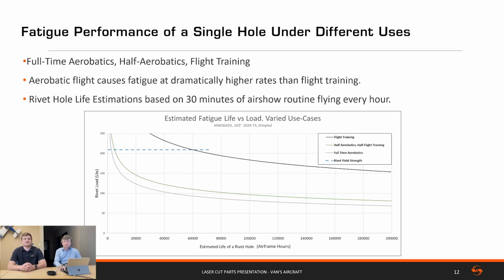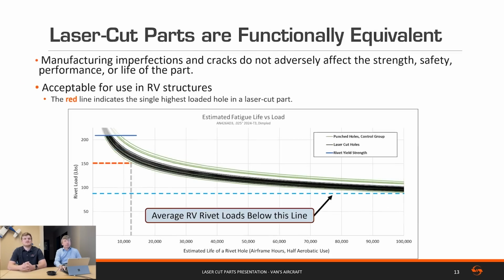So these calculated service lives for these holes are given in units of an airplane that is flying half of its time in aerobatic flight, which is dramatically higher than any known case. 30 minutes of every hour, effectively 2 professional airshow routines every hour of flight. And that has a very dramatic reduction in the performance of those holes, and that leads to significant conservatism in this data. This is another way of looking at the data from these holes.